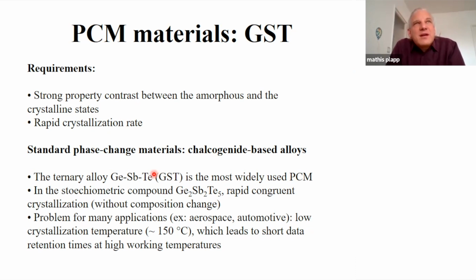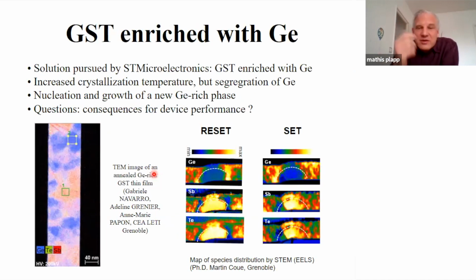But if you define that you want to keep your data, say, for 1 year, then the crystallization temperature of normal GST 225 is 150 degrees Celsius. If you heat it up more than that, then it will rapidly crystallize. And this obviously means that you lose the information, because in the end, everything will be crystalline, and then you will have wiped out everything that was programmed there. And this is annoying, especially for many applications envisaged in the automotive sector or in aerospace. When you want to be close to a motor, you would like to have devices that keep working at higher temperatures. And so ST has found a way to do that.